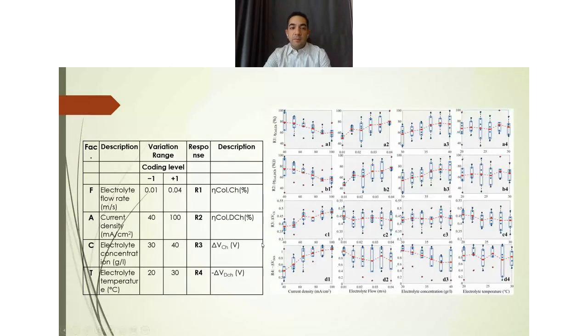So while varying the different values of these operating parameters, you can see that, for example, for current density, in case you increase it and see the effect of this increment on the Coulombic efficiency of charge, you can see that it will reduce it. But if you increase the flow rate, you can see that it can generally improve the Coulombic efficiency as it is increased.